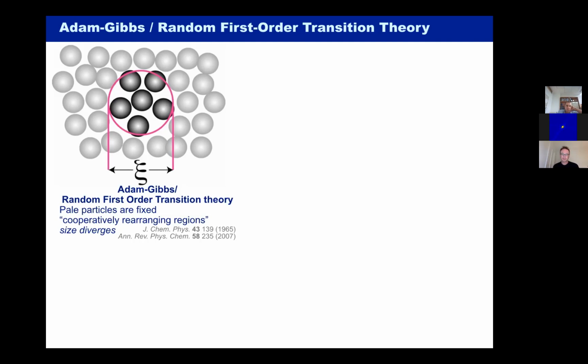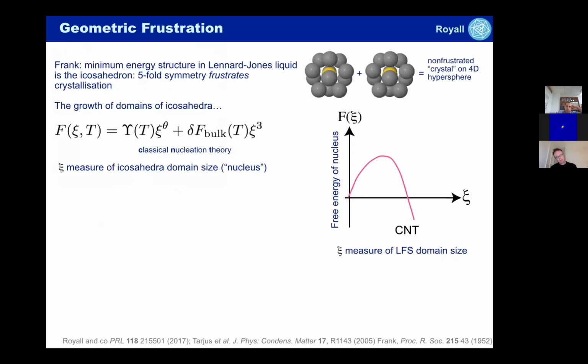And it turns out that the size of these cooperatively rearranging regions, which are written here as Xi, gets larger and larger and larger as we drop the temperature and head towards the glass transition. So this theory is thermodynamically based, and the reason it's thermodynamically based is that it imagines that in our cooperatively rearranging region, we have a limited number of configurations. So in my cartoon, I have 2 configurations within that region that the particles can access. As my entropy becomes less and less, if I still want to have 2 configurations, I need a bigger and bigger region for the particles to undergo this cooperative rearrangement in. So this theory imagines that there's a drop in the number of configurations that the system can access as we drop the temperature.